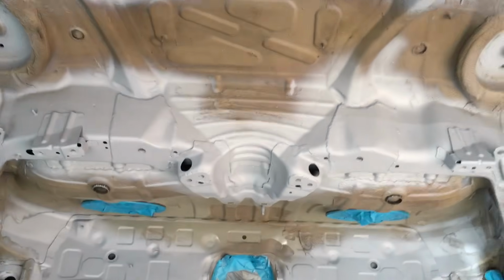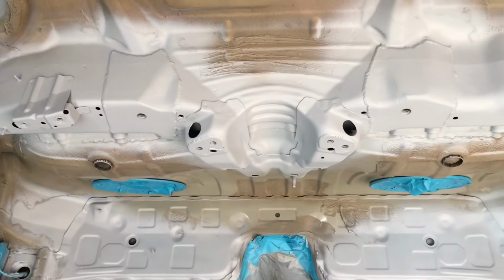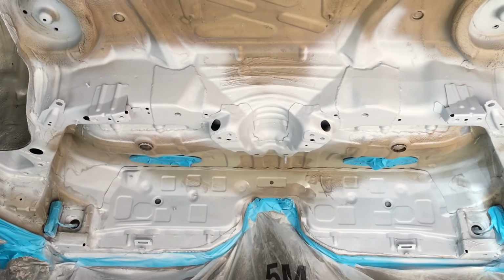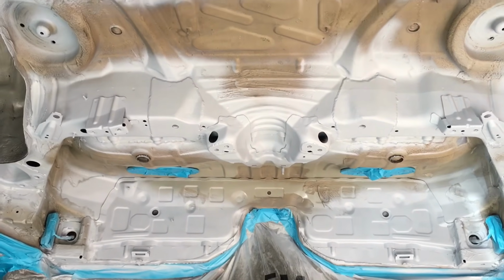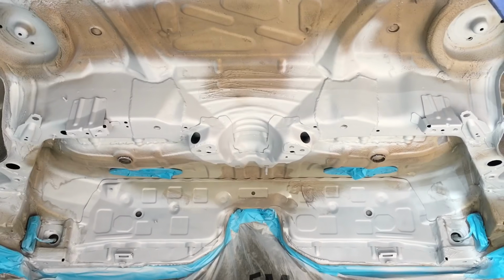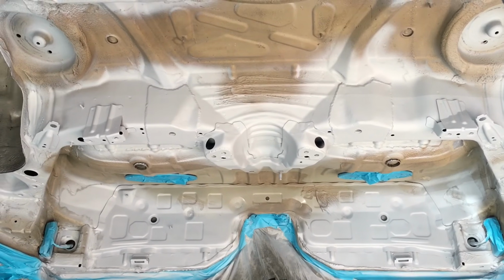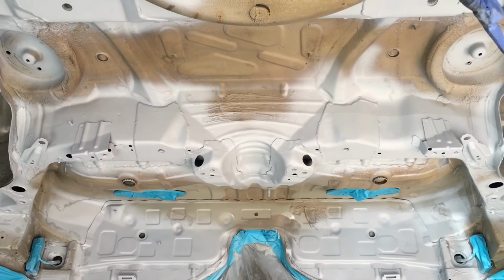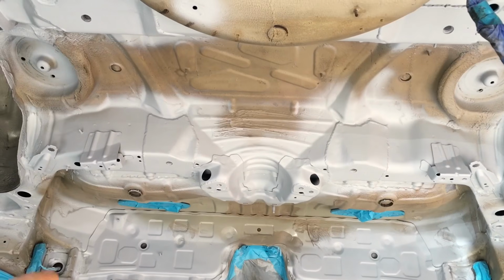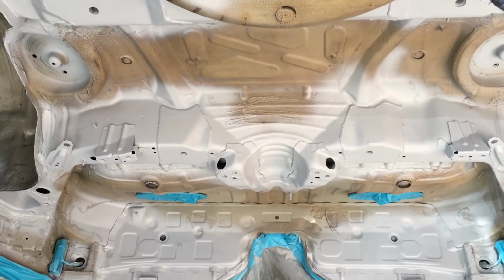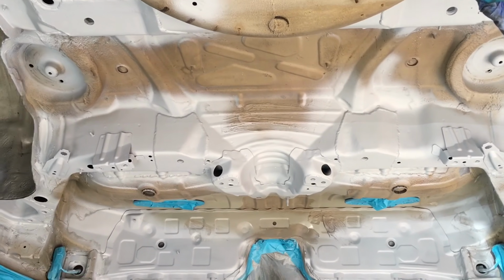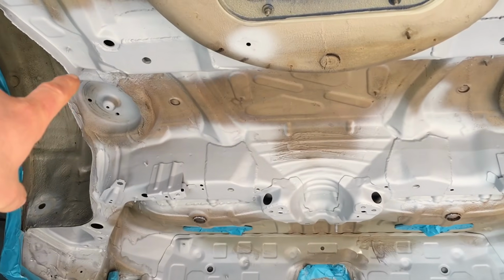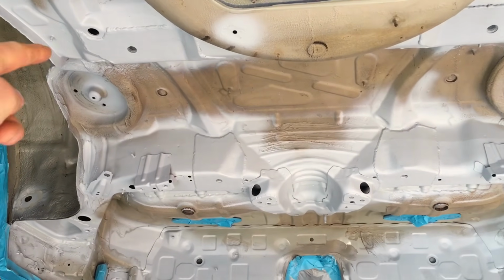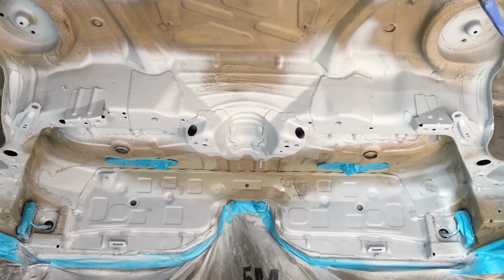We've also, before we've done, it's now in etch primer as you can see, but before that etch primer was carried out, we've applied the POR 15 metal prep solution, which is a chemical which neutralizes corrosion and coats the chassis or the bare metal areas with a zinc phosphate coat, ready for good adhesion of the next layer, which is this one you're seeing now, which is etch primer. We've also taken care of a spot weld that was broken up in that area there and stitched the rest of that panel on the left rear of the wheel arch lip.